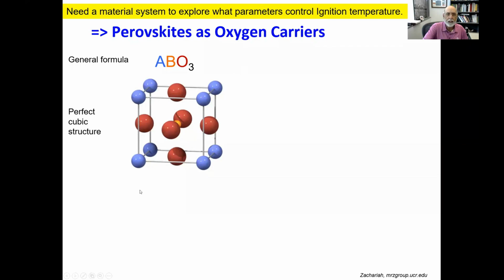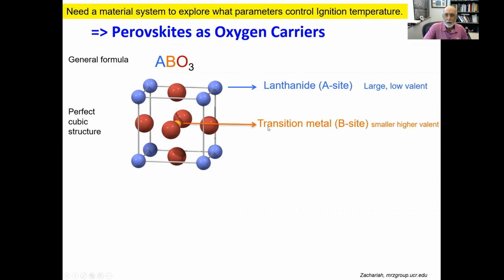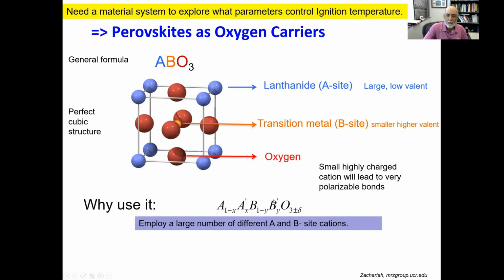But for our purposes, because they have this very regular structure, and they have this ABO3 chemistry, where A is a lanthanide, which is the A site, which is a large, low valent metal. And the B site is usually a small transition element. And then the red ones are oxygen. The advantage is that you can mix and match, well, not any kind, but a variety of different compositions and still keep the same crystal structure, which is important for us. So I'm going to approach this from the point of view of changing the redox properties.